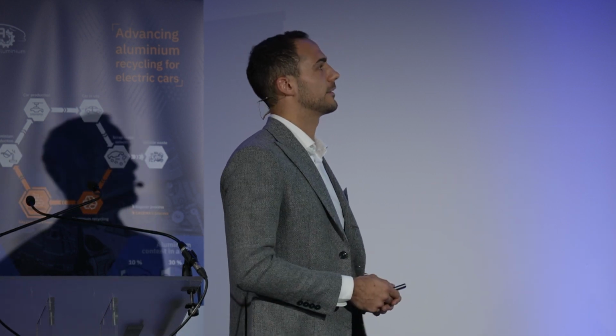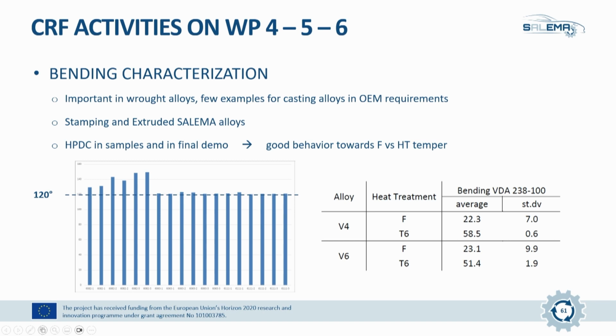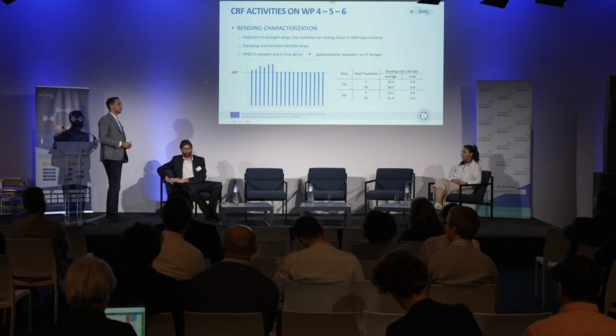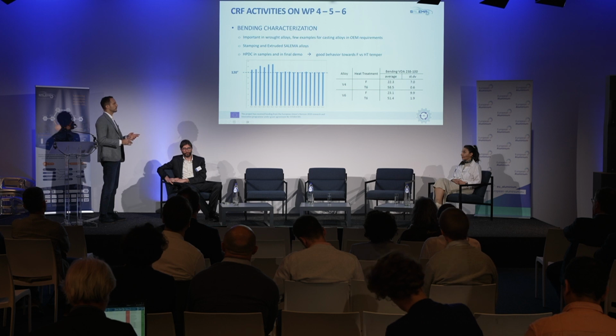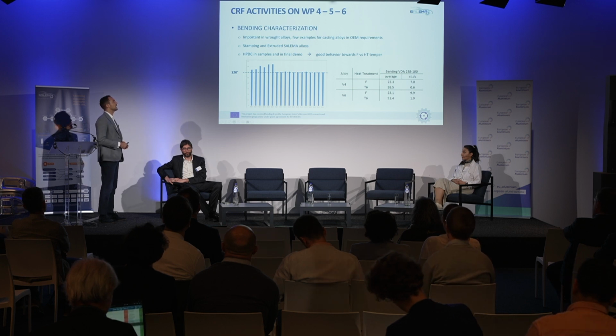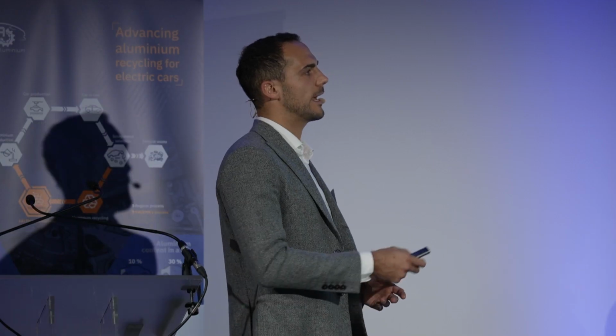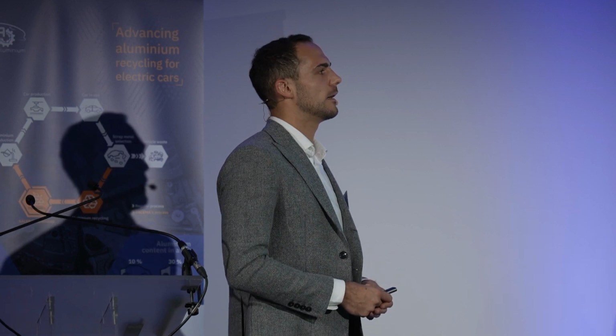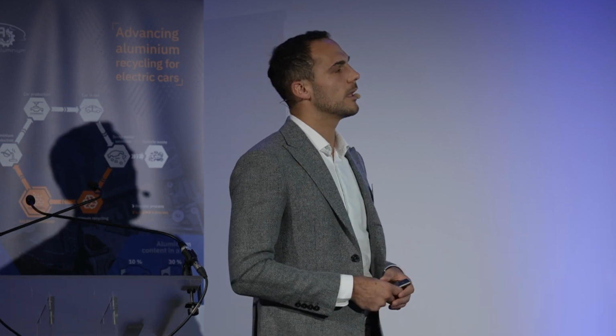Then the bending test. The result on the left helped us choose the best variants and the best alloy. We did it also on the casting, even though few OEMs require bending tests on casting. Again, we had good behavior, even at sample level. Now we are continuing the characterization on the demonstrator.